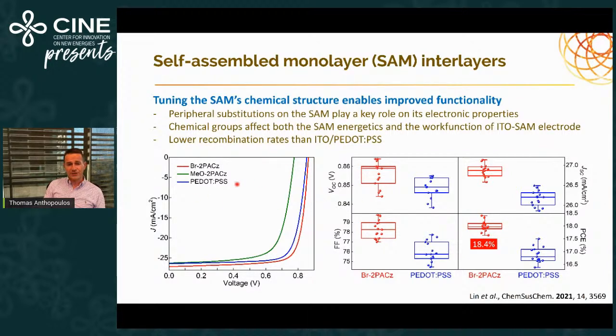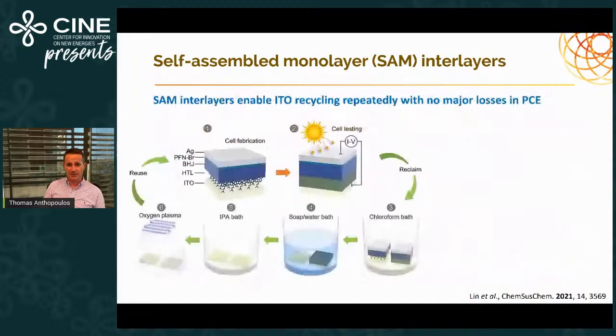And then we change with the different SAMs. This one, the green line, you can see that you're losing a lot in the VOC. Perhaps the work function relation is dramatic, and we see a kind of linear scaling between the work function of some modified ITO electrodes and the overall VOC, which is very, very encouraging. But the moment we have the brominated version, essentially we have a much stronger dipole, a much deeper work function of the electrode, and a much more favorable interface between the bulk heterojunction and that ITO functionalized with a SAM electrode. And essentially this allowed us to demonstrate OPVs with efficiency of 18.4%.